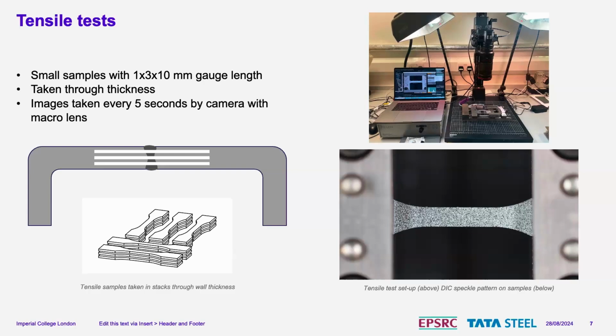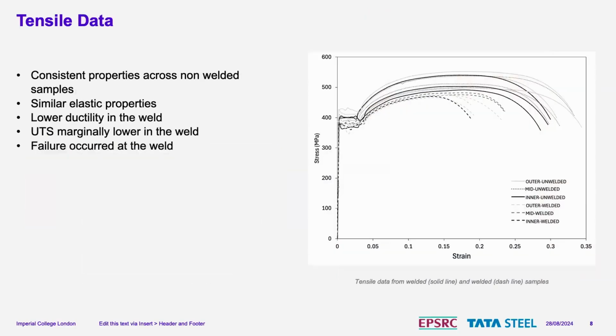And if we go to the next slide, this is my data. So just to explain, there's a lot of lines here. These ones around here and going over the top, essentially solid lines are unwelded material. Dashed lines are welded material. We've got some dotted in there just because the solid gray was hard to see. But you can see that essentially we've got the same elastic properties, pretty much the same yield points, and up to around the UTS, then it's all largely the same. Yes, there's some scatter, but that's to be expected from small samples.